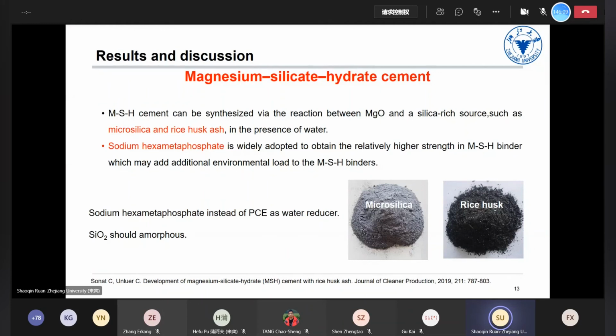And also in terms of solid waste, researchers normally use microsilica. However, some researchers also use rice husk ash as the solid waste to produce the M-S-H cement. However, this silicon dioxide should be amorphous. If it is crystalline, the strength of the M-S-H is quite low, so it may not be very effective in the SS.